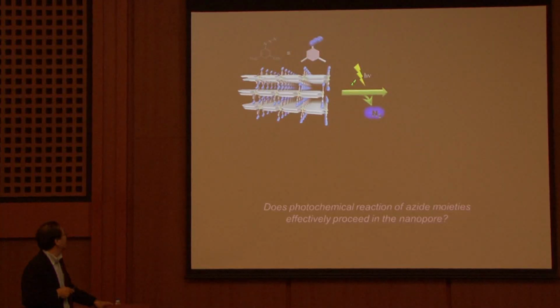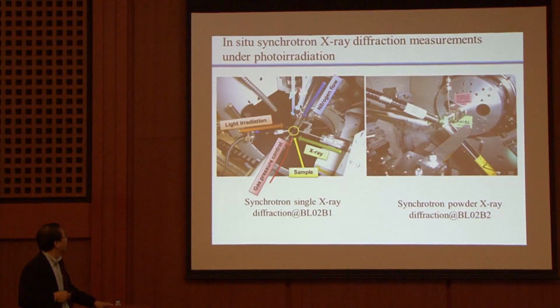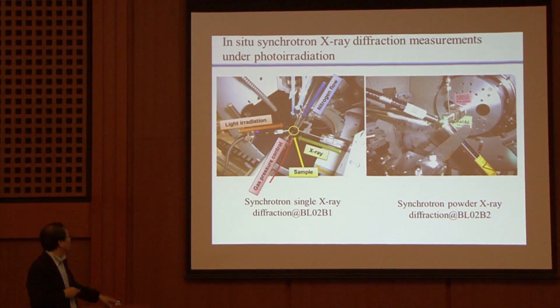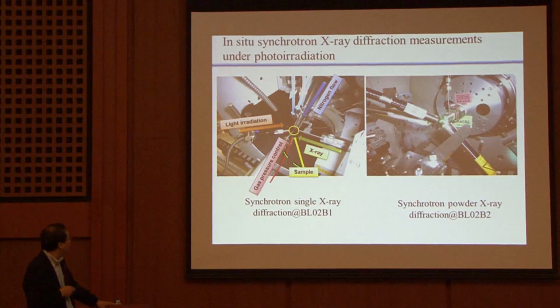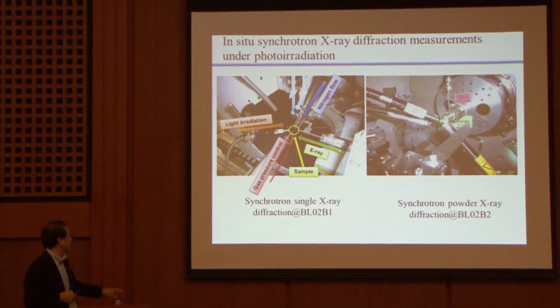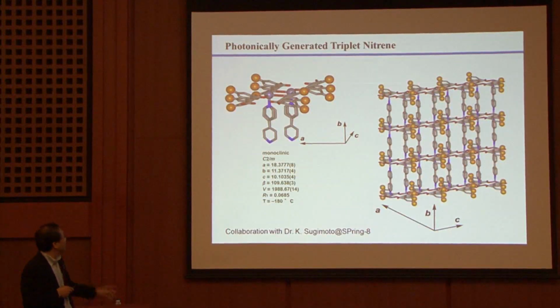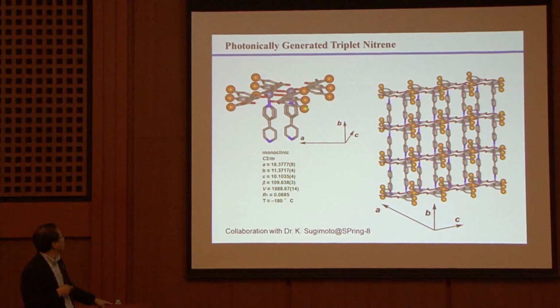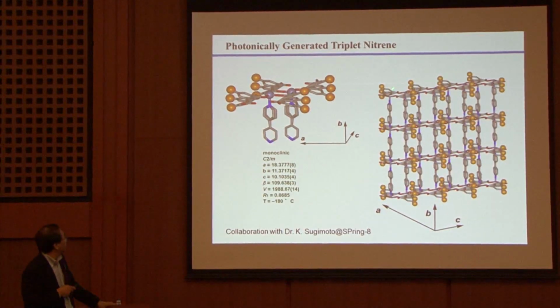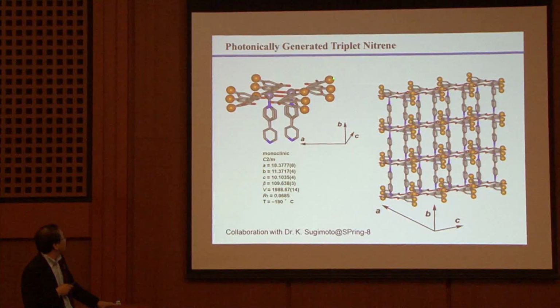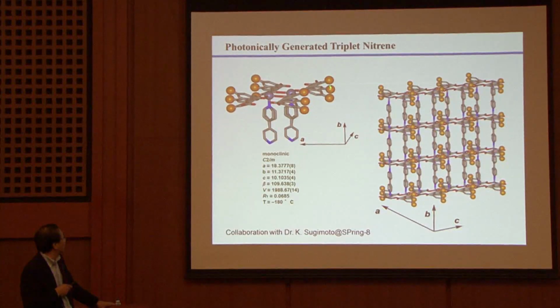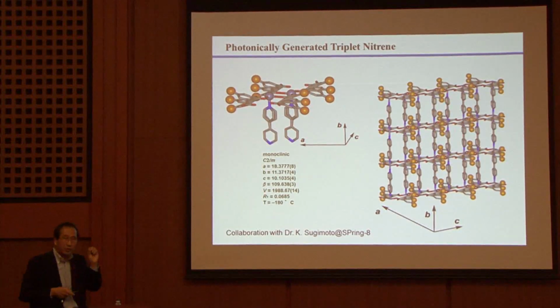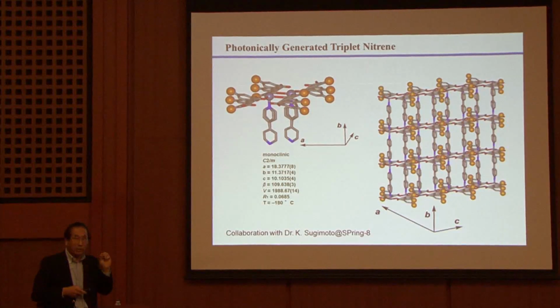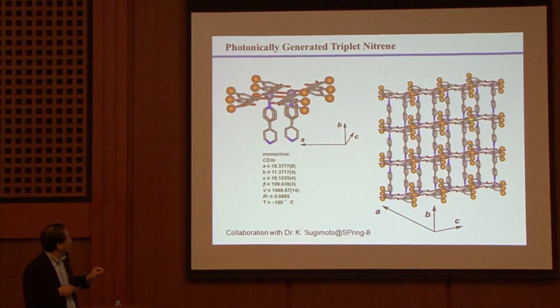By irradiation, nitrene is generated. So what happens? We observe the crystal structure in situ. This is the result. This is the framework, and this is the nitrene. Of course, there is disorder over three sites. But this is the nitrene.